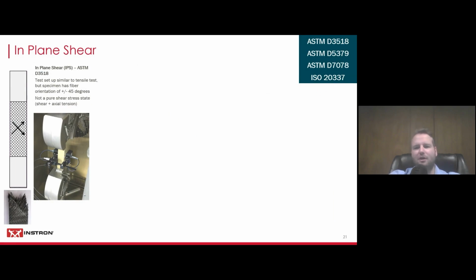The most common testing standard here is ASTM D3518, and there's a variety of other shear tests that you can run. So for in-plane shear, there's the D3518 test right here. It is the same as D3039, but your specimen has the fibers oriented in a plus and minus 45 degree orientation, which gives you a nice shear failure like you can see down here. Now it's important to note that this is not a pure shear force that you're recording. There's always an actual tension component in there. So this can give you a good idea of your shear strength, but you're not really able to use that result as a shear property.